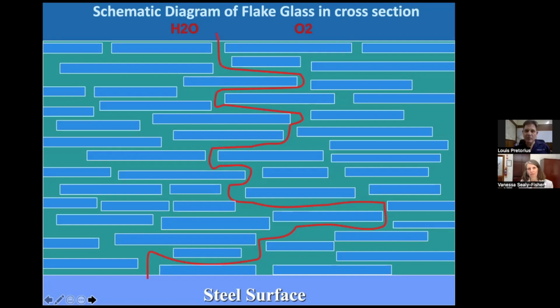And this is the principle of the tortuous path. And the principle of tortuous path is important for all the different users and manufacturers of flake-filled resin systems around the world. You can imagine them as little fish scales. And if you can put in 100 layers of fish scale in 500 microns or in a millimeter of coating thickness, you can imagine that the barrier properties of that barrier against diffusion is substantially higher than the identical resin system or coating without flakes. The additive, yeah, so that makes a lot of sense.